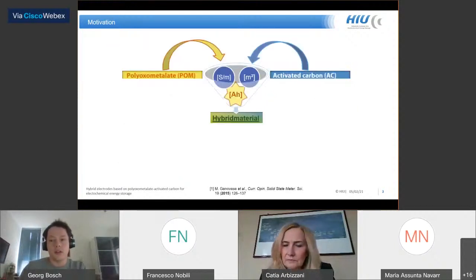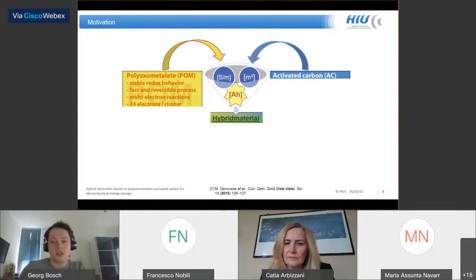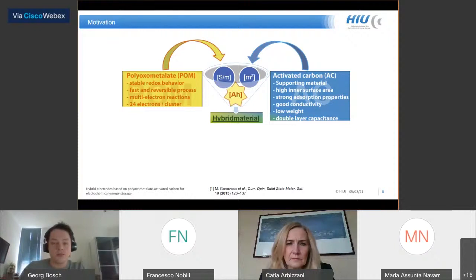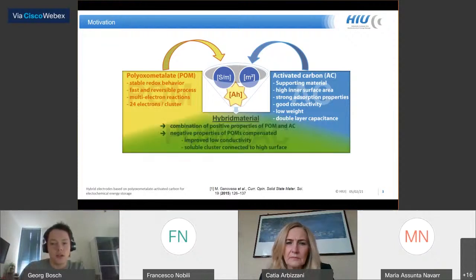Therefore, polyoxometalates and activated carbon were chosen. Polyoxometalates are stable against oxidation and reduction reactions and can absorb and release up to 24 electrons in fast and reversible multi-electron reactions. On the other hand, activated carbon can act as a supporting material, which has a high inner surface, high adsorption properties, a good conductivity, a low weight, and also double layer capacitance. The hybrid material can combine the positive properties of both materials, and negative properties of polyoxometalates, like their good solubility in polar electrolyte and weak conductivity, can be compensated.